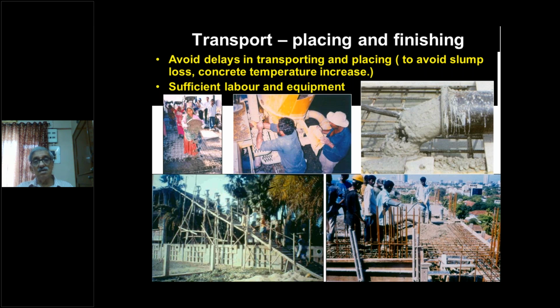The other way concrete can jam your pipe is by segregation of the mix. Now when concrete is pumped, there is a lot of pressure, and if the mix is not cohesive enough, it will segregate. And once the concrete segregates, the finer material is consumed, it has gone out of the coarser material, and you will get a honeycomb type of plug which has jammed the pipe. So in your future mixes, you have to be careful. Concrete has to have good workability and also lesser chances of hardening should take place in case of stoppages.